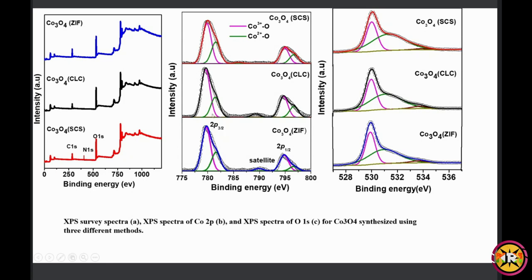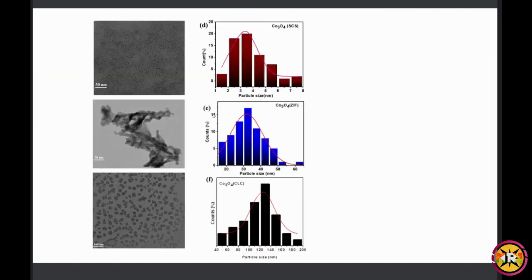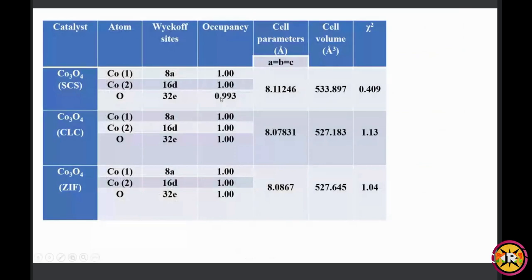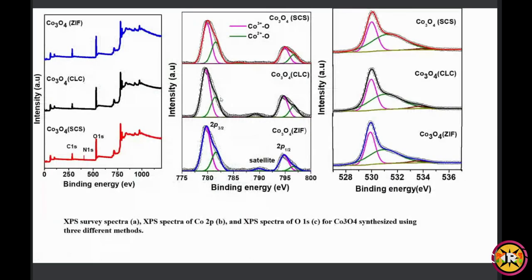So now from here I have calculated the cobalt 2+ by 3+ area. As I have mentioned, from Rietveld refinement I saw some oxygen came out from the lattice site. The oxygen occupancy is not exactly 1. Like here you can see oxygen occupancy is not exactly 1. So some oxygen came out from the lattice. But Co3O4 is neutral, so if some negative charge comes out from the lattice, there should be some reduction of positive charge also to maintain the charge neutrality. So the cobalt 2+ by 3+ ratio will also increase if the oxygen vacancy is increasing.